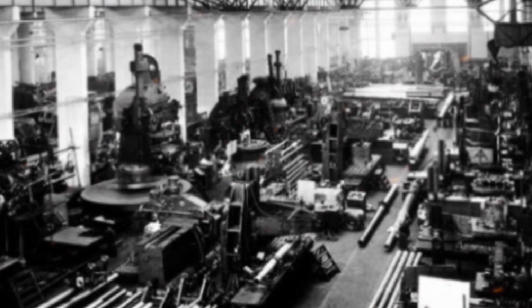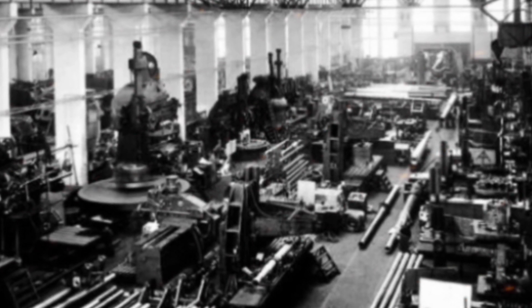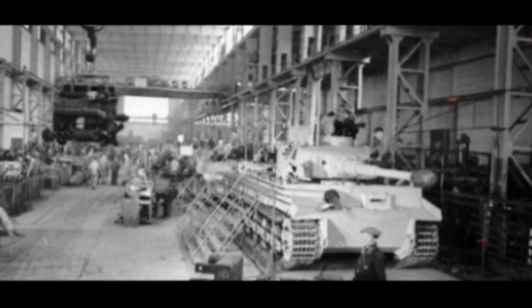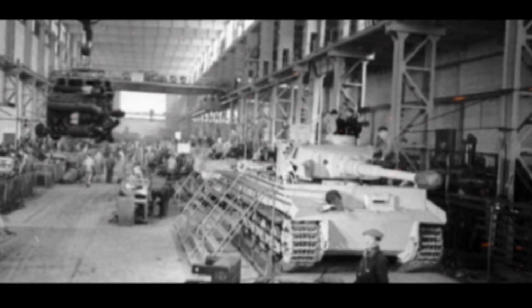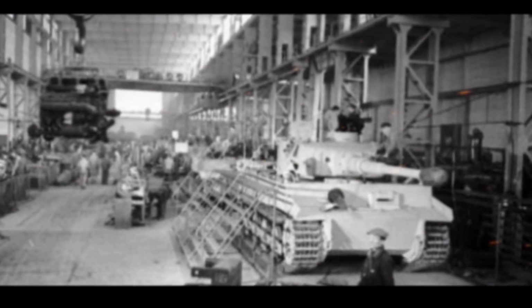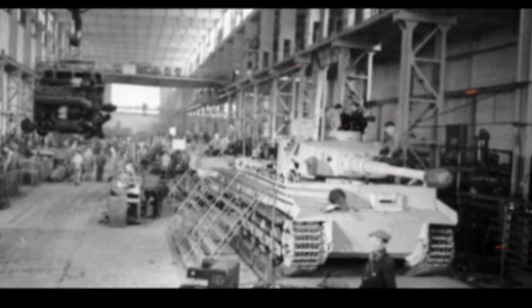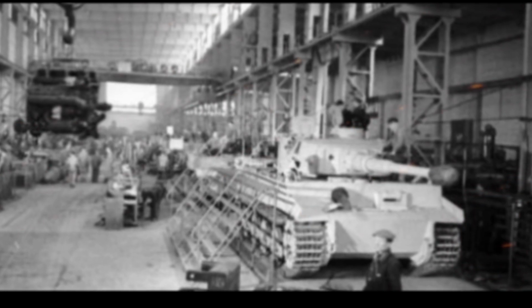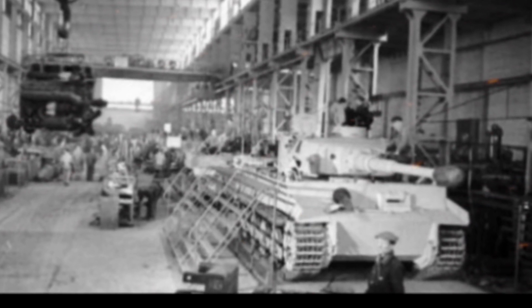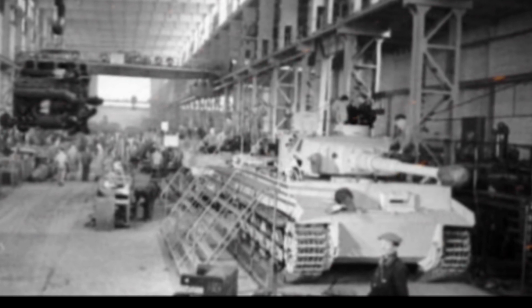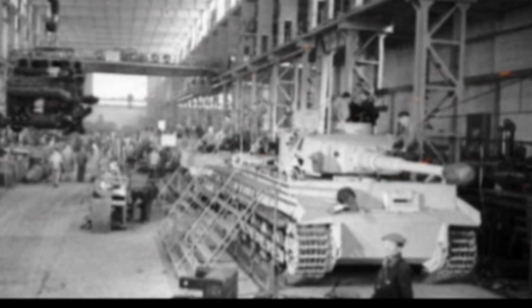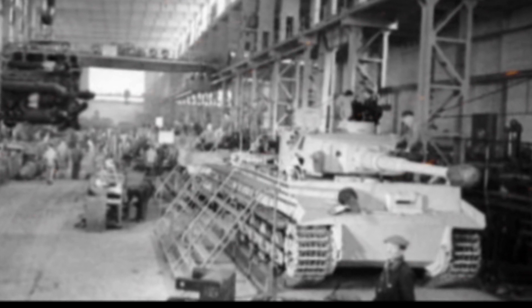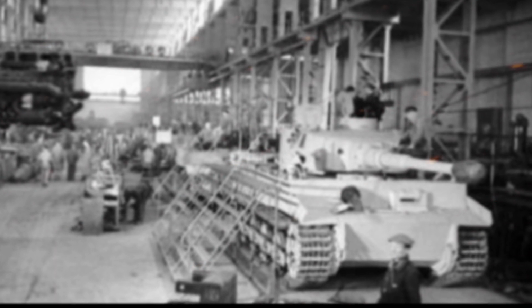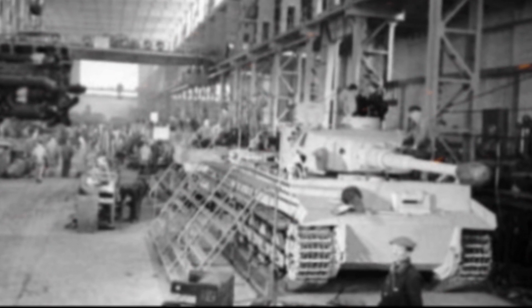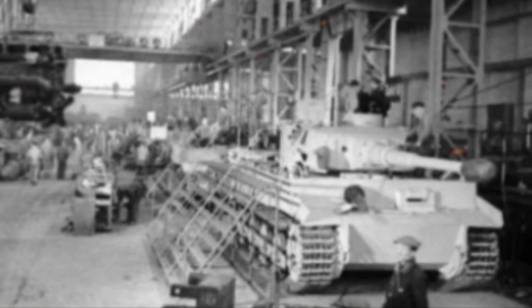Stephenson examined 6 more failed Tiger gears over the following days. Every single one showed the same pattern: excessive surface hardness, deep case depth, untempered martensite, brittle fracture. This wasn't a fluke. This wasn't one bad batch. This was systemic. Every Tiger transmission was being built with gears that had inadequate heat treatment. They were too hard, too brittle, and they would fail under the stress of normal operation. Sharp turns, sudden stops, rapid accelerations, the kind of maneuvering you do in combat. Those maneuvers create shock loads on gears. Properly treated gears can absorb those shocks. Tiger gears couldn't. They shattered.